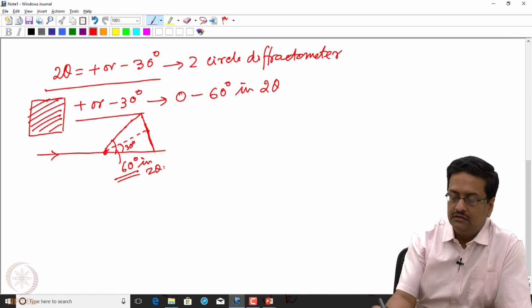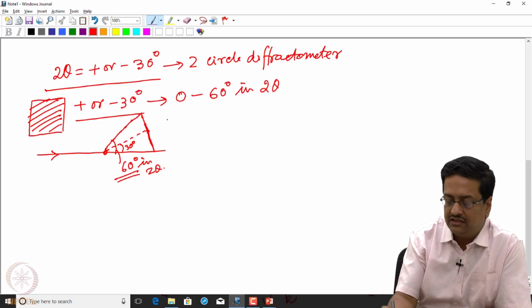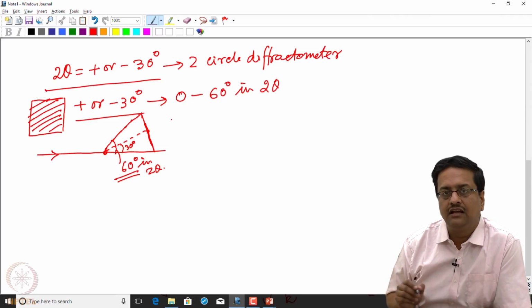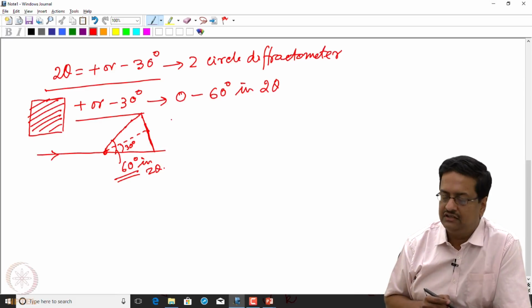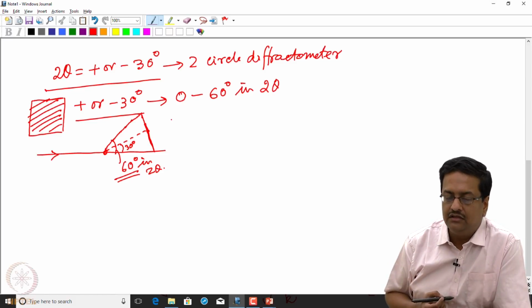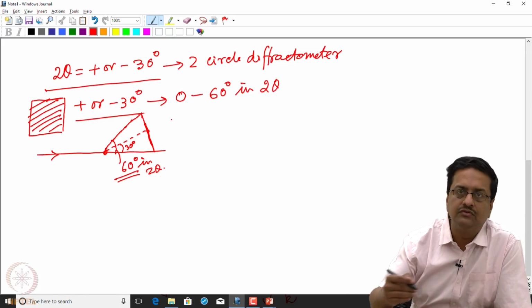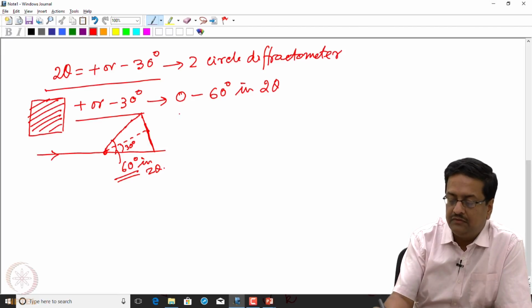And what is the limit for IUCr using molybdenum data? Mind you, for routine single crystal X-ray diffraction, everyone uses molybdenum because it has much higher penetrating power and it gives much less absorption, and it can then collect the required data with less amount of 2 theta span. So we collect this data using molybdenum radiation,